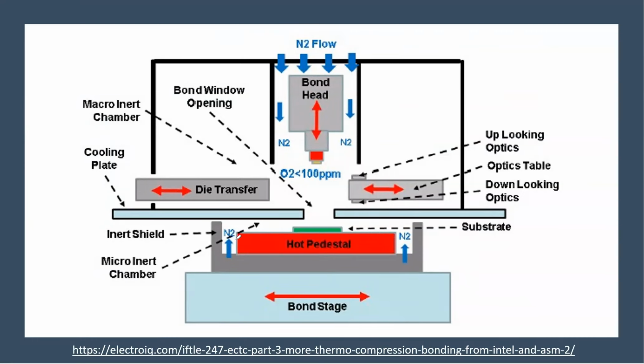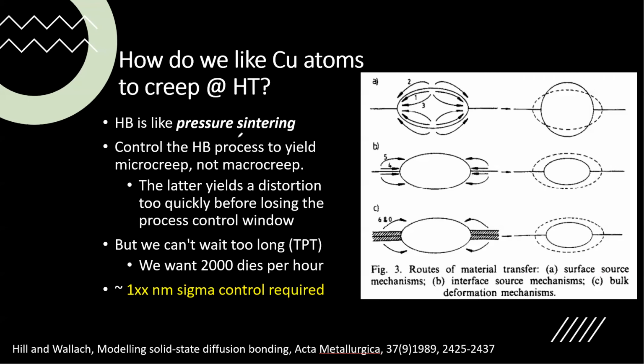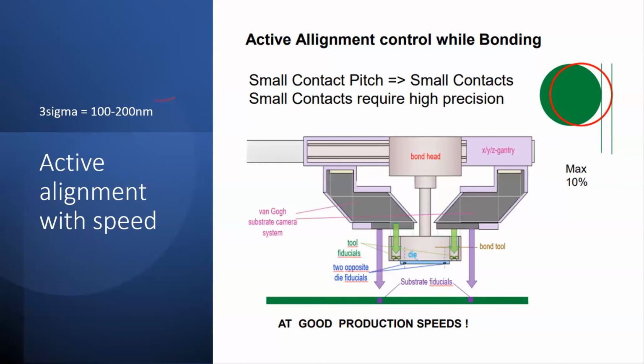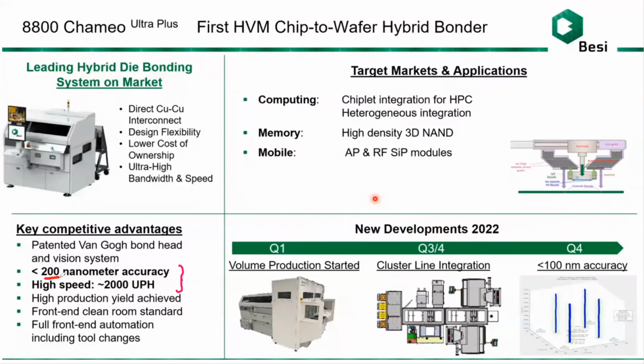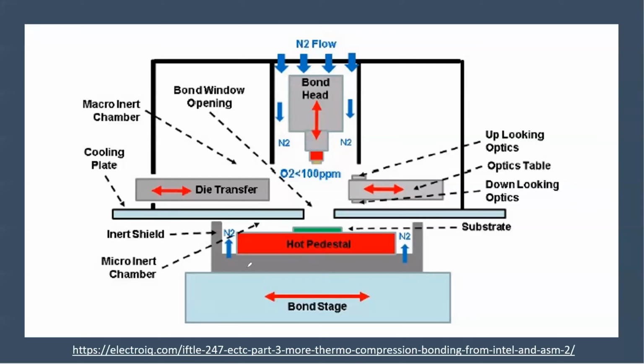When you're bonding, actually, you are doing this so-called pressure bonding, okay? Which means that you creep at a certain high temperature. This high temperature is not that high. 150 for dielectric bonding, less than 300, or a little bit higher, for the copper bonding. Okay, so that's what you want to control in a way that gives you 200 nanometer accuracy, high speed, 2,000 units per hour. All right, with this kind of schematic to show you the flavor of it. And it turns out very few companies can do that properly.